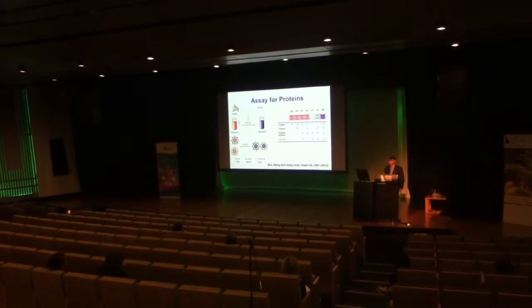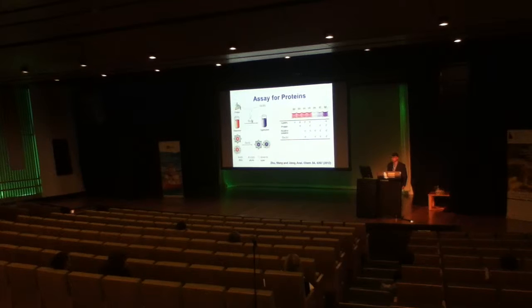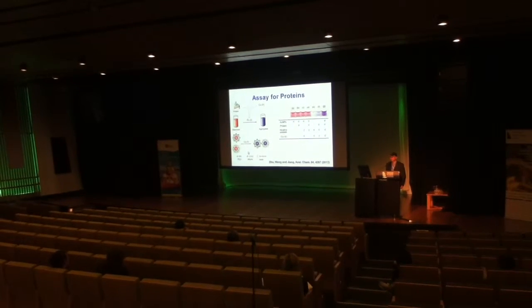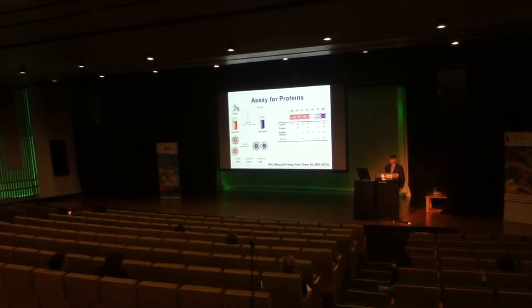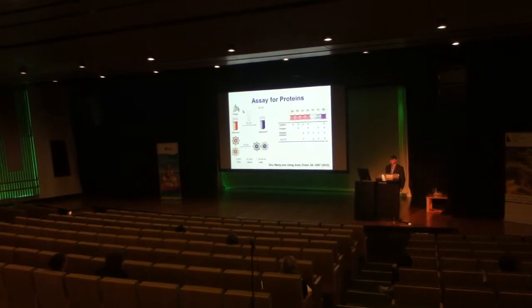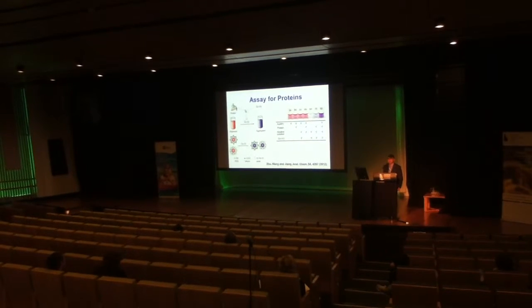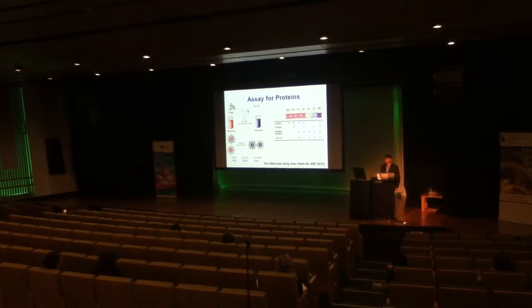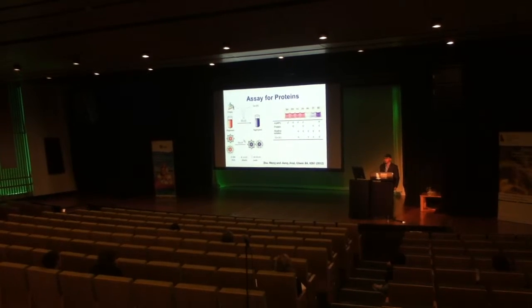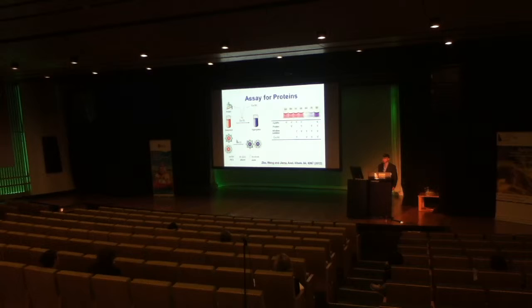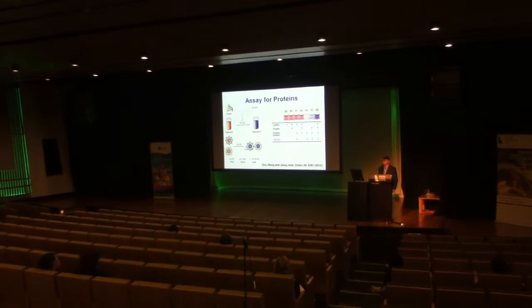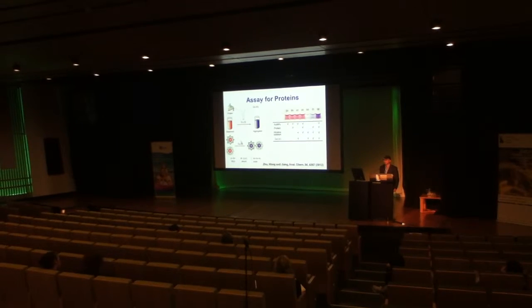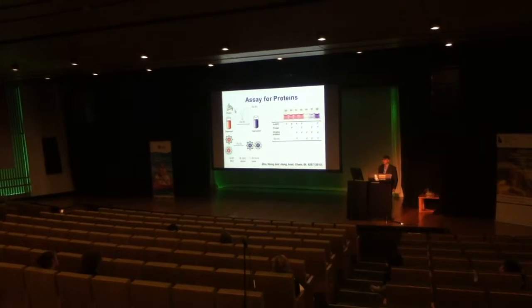So basically, because we have this copper-based assay based on gold nanoparticles, we could actually use the protein as a reduction agent, as a reductant, to quantitatively determine the amount of reductant in the solution using this strategy. Again, we use the presence or the creation of the copper-1 as an indirect assay for the presence of proteins in this case.